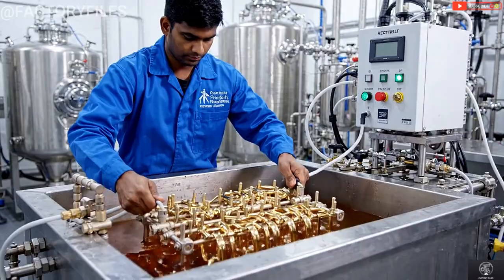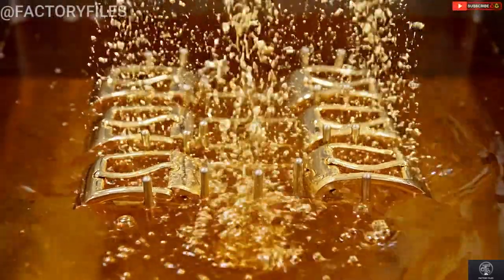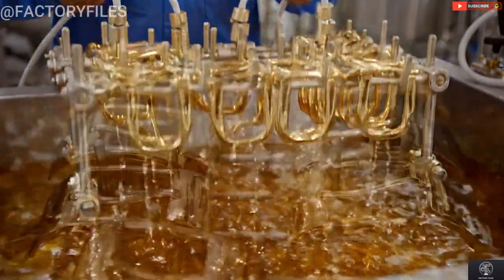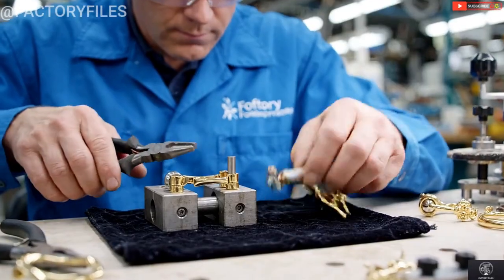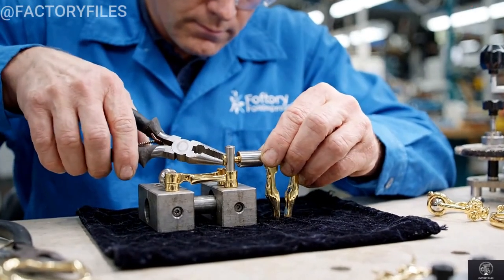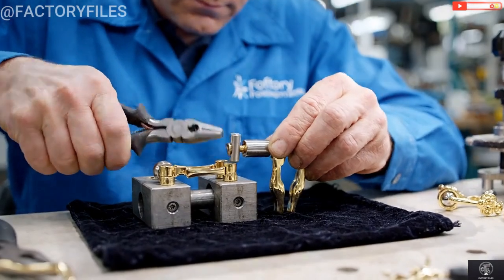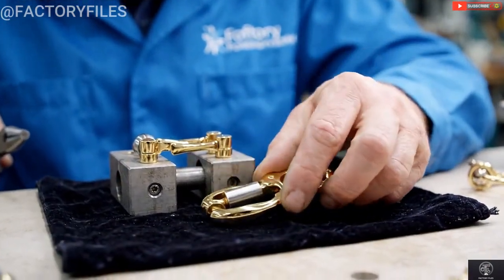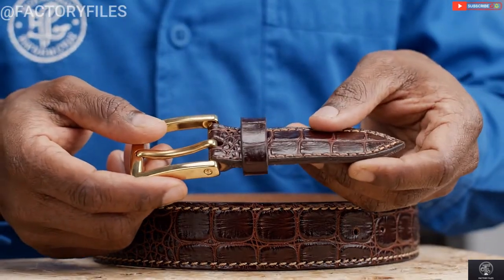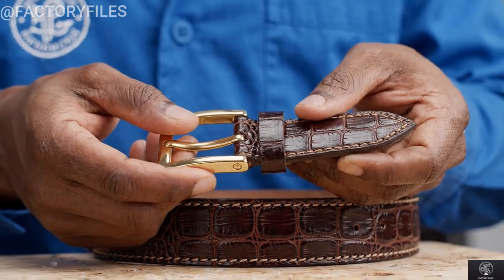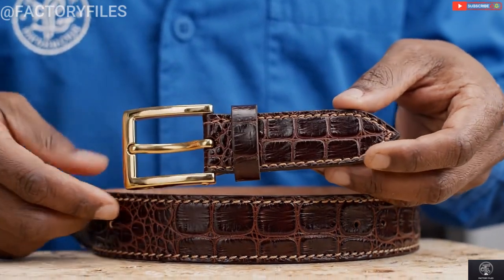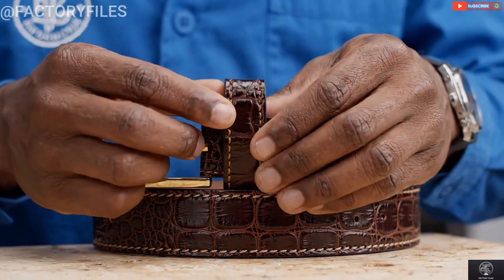The polished brass buckles enter an electroplating bath, where a controlled electric current deposits a micro-layer of 24-karat gold or palladium onto the surface. Using custom fixture blocks and soft-jaw pliers, the assembly worker fits the prong and roller sleeve into the buckle frame. Then, the skived end of the finished belt strap is threaded through the gold-plated buckle frame, and a matching leather keeper loop is slid into position beside it.